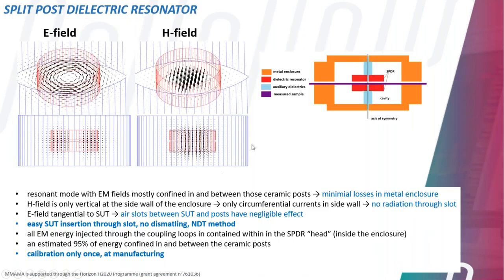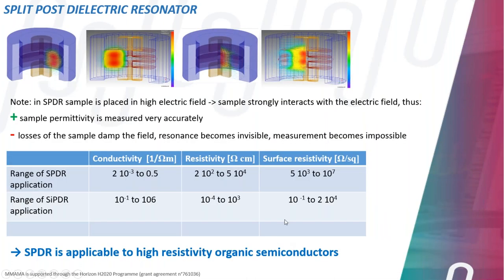So we will use cylindrical resonators, and additionally we will put this high permittivity ceramics inside. What is the result? The high permittivity ceramic, again from the Maxwell equations, will have a tendency to attract and focus the electromagnetic energy. So the energy storage will be mainly in this red resonator structure. You see it on the pictures. We have very weak fields when we come to the cylindrical shield, which means that our losses in metal are further minimized. Our sample will be inserted in between these two posts. And we do not break current lines by making a slot.